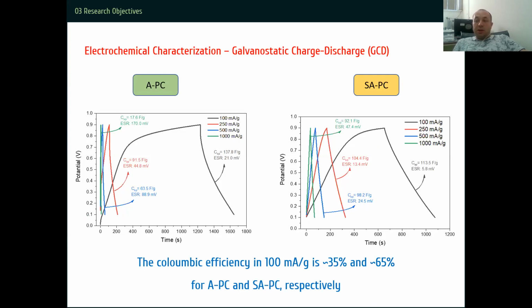Therefore, we worked at higher current densities, and it is found that the specific capacitance of SAPC sample is very high compared to APC sample, almost 50% more. You can see at 250 milliamps per gram current density, the specific capacitance of SAPC sample is almost 104, and at this current density, the specific capacitance of APC sample is almost 90.